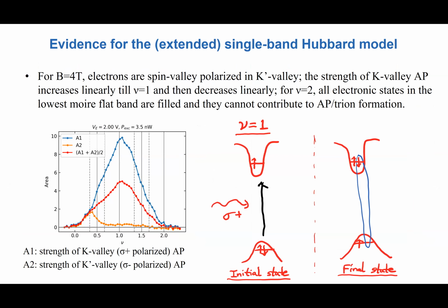And if I occupy each site, I cannot form these excitations, and that's why the oscillator strength is going to go down. So that basically is a strong indication, I'm not ready to say proof, that the physics up to nu equals 2 is describable by a single band Hubbard model, right? So I start occupying sites, and this is at a large magnetic field. So basically, this is the light induced depolarization effect. The oscillator strength of one polarization remains zero because I cannot make any excitation of the same spin.